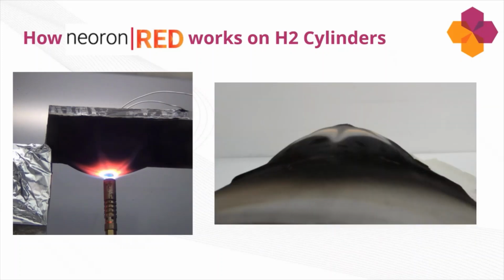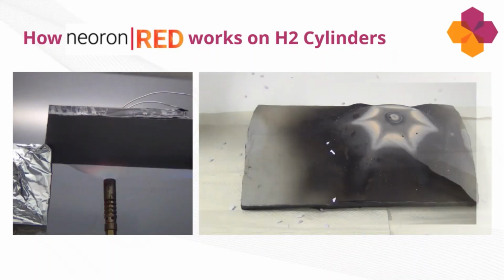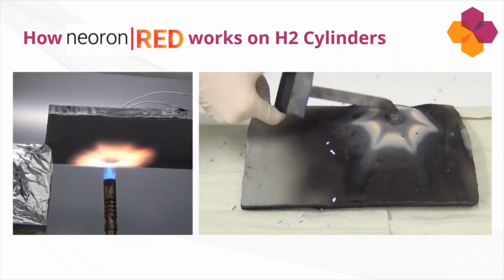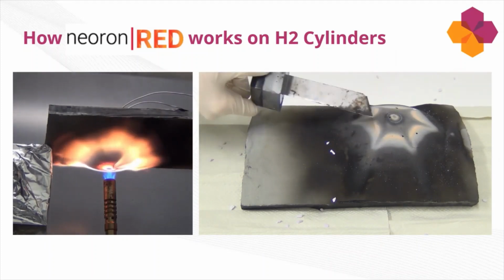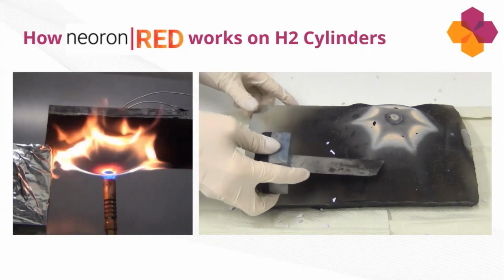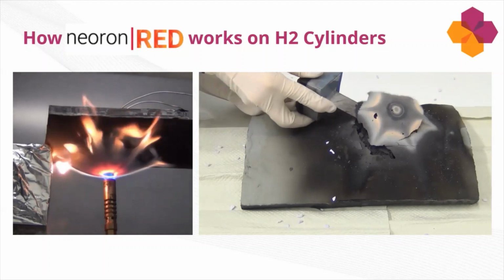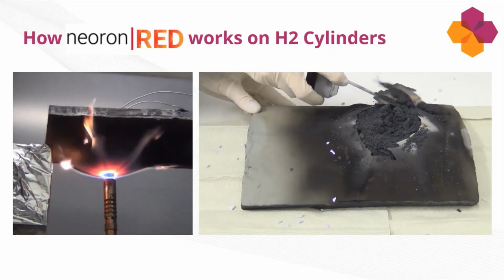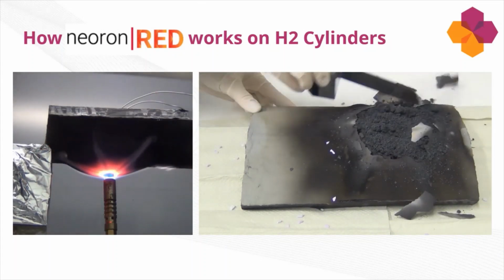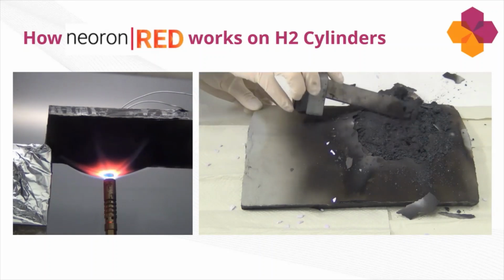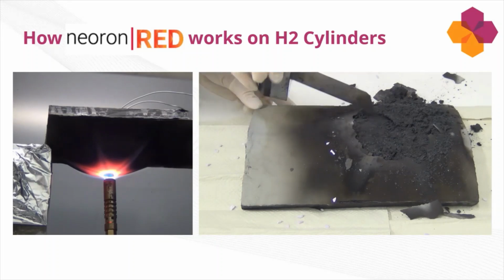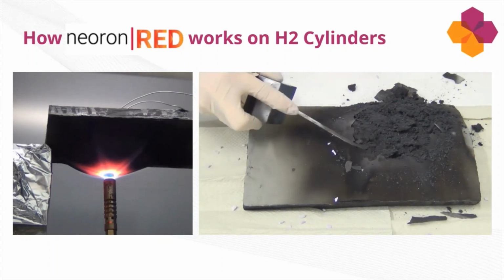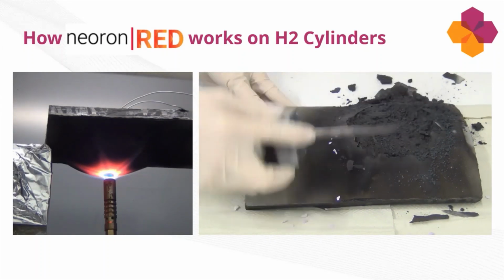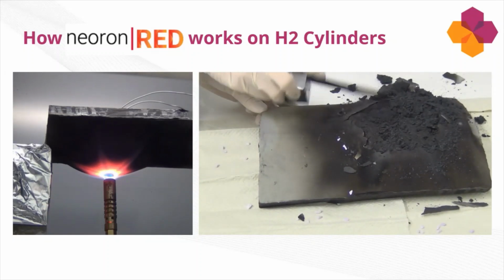The next slide shows you how much the expansion really happens on the surface. It's a really nice expansion and very nice thermal protection for the substrate itself. If you look at the composite after burn, you can see there's a hard ceramic shell, and then you really have to dig into that, which we will see in a minute. When you dig into that, you can see how much thermal isolation is found underneath, and that will give you real protection for the substrate. Without the ceramic shield on top, there would be just a drilling effect, where the expansion will just continue and continue, and then the flame, the Bunsen burner, will just drill through that foamy substrate and go to the real composite substrate. But now it cannot penetrate the substrate because there's a ceramic shield preventing that.